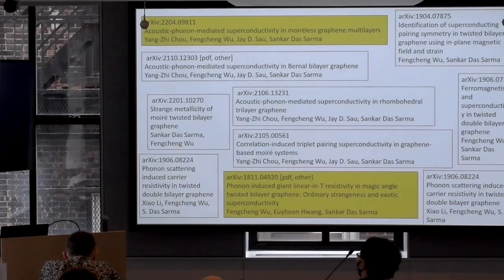What is universal is that there is a regime where it's linear. And the electron phonon coupling that you need, if you just do a back of the envelope thing, is strong coupling, the age of strong coupling superconductivity. You need something like 1.5 to get the correct resistivity. What you cannot get is going down to below 10 Kelvin, because if you convert into an effective free electron model, then the cuprate electron density is of the order of 10 to the power 21 per cubic centimeter. So instead of 10 to the power 23, it's 10 to the power 21. That's a factor of 100. In K, that's a cube root, but it's still a factor of 5 or 6. So that means if aluminum is linear down to 50K, a cuprate could be linear down to 5K just from the Fermi energy difference.